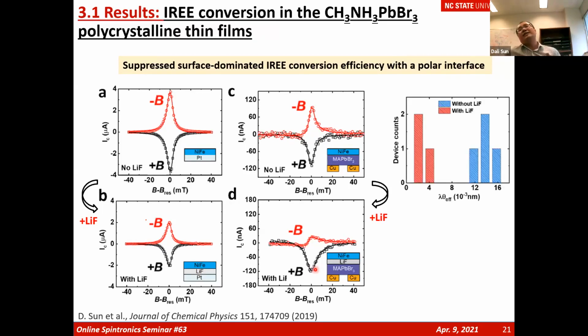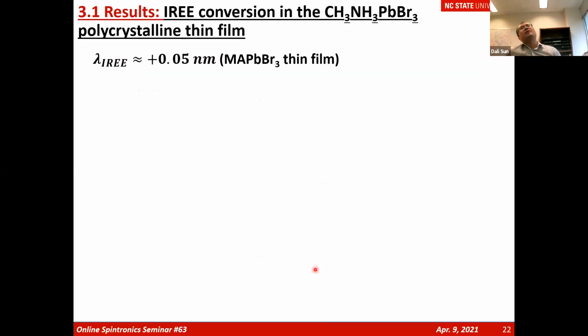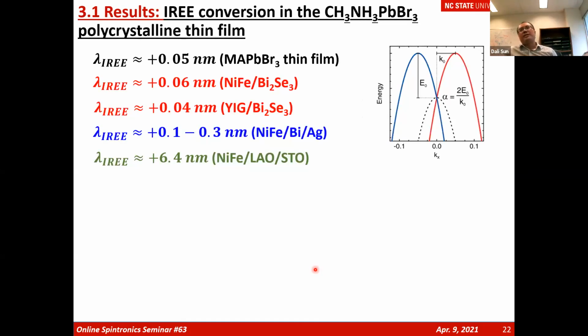It turns out after adding the lithium fluoride, the spin-to-charge conversion efficiency is significantly and statistically lower compared to the bare interface between the nickel iron ferromagnet and the MAPbBr3. This means the spin-to-charge conversion efficiency comes from the interface, which can be understood as the inverse Edelstein effect conversion, related to the Rashba state. So then we can do our estimations. We observed a λ_IEE coefficient up to 0.05 nanometers, compared with typical Rashba states in bismuth silver and LAO/STO. It's comparable, but not that large.